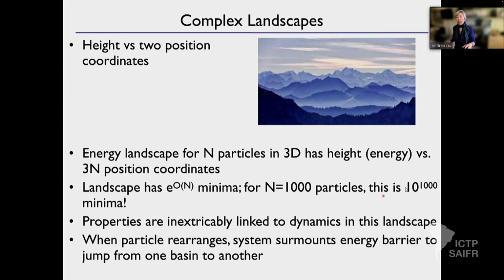Because think about what happens at high temperature, right? You're floating above all the peaks, okay? Any particle can relax at any time, okay? Can rearrange at any time. That's an ordinary liquid. Now, as I lower the temperature to fall somewhere among these peaks, right, you can start getting trapped and not being able to go over saddles into other minima. And so the dynamics of how you traverse this landscape are related to the properties of your system in that landscape. And that's what makes the problem hard.